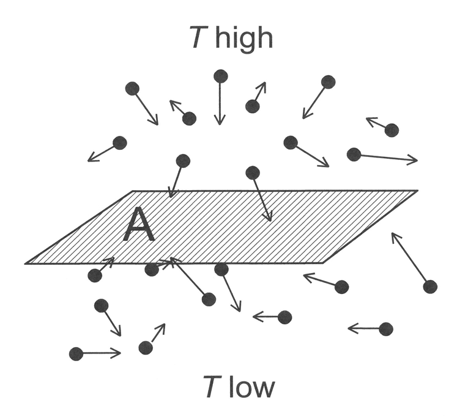Thermal anisotropy. Some substances, such as non-cubic crystals, can exhibit different thermal conductivities along different crystal axes, due to differences in phonon coupling along a given crystal axis. Sapphire is a notable example of variable thermal conductivity based on orientation and temperature, with 35 W/mK along the C-axis and 32 W/mK along the A-axis. Wood generally conducts better along the grain than across it.